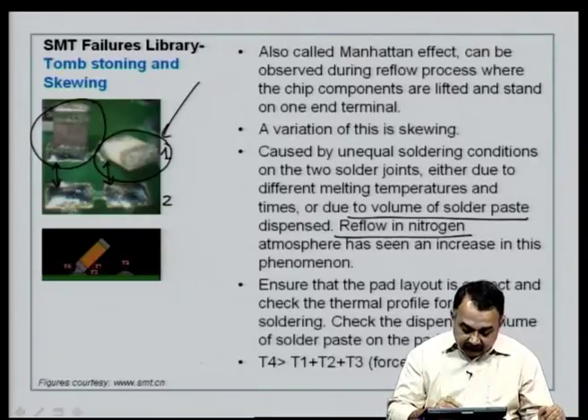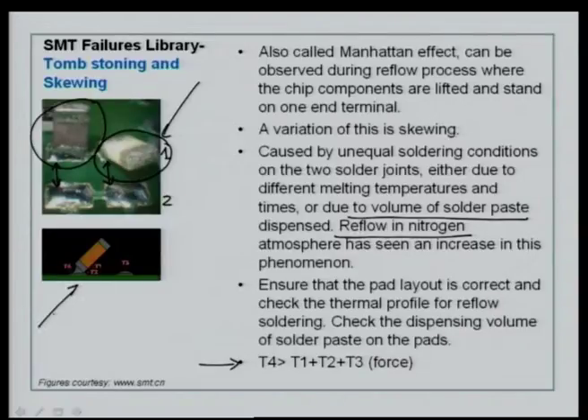And typically what you see here in the point that I have mentioned at the bottom, and if you relate it to the figure here, the force T4 which actually lifts the component from the base of the pad is very much larger compared to the force exhibited by the solder paste at this end, the force exhibited by this terminal stub on the other pad, and then the weight of the component. Therefore, what has happened basically here is this solder paste has got activated much faster. The melting temperatures have been attained in a much lesser time compared to this pad and the solder paste, and therefore, this solder paste here by surface tension has pulled the component towards its side, and it is not at all attached to this pad.